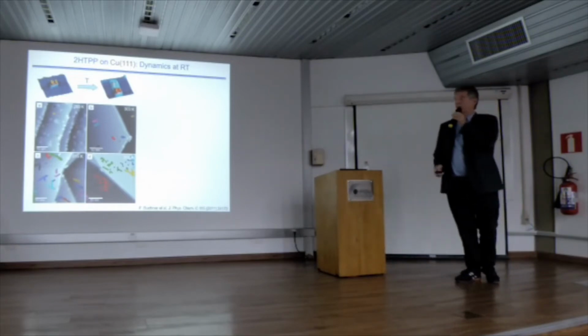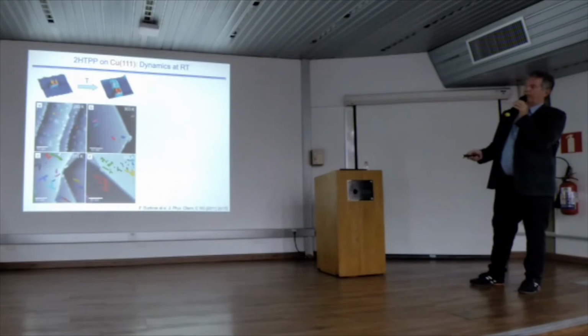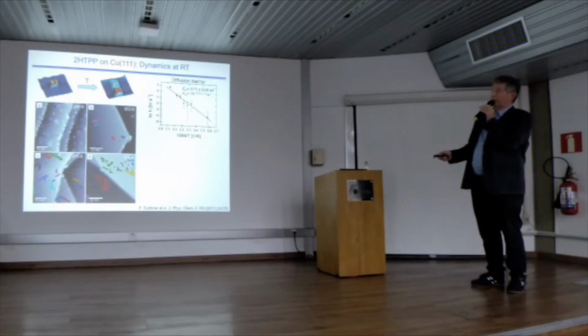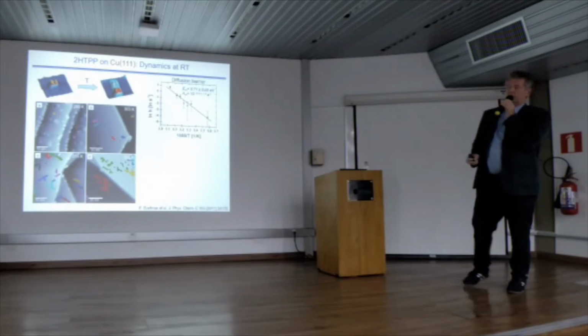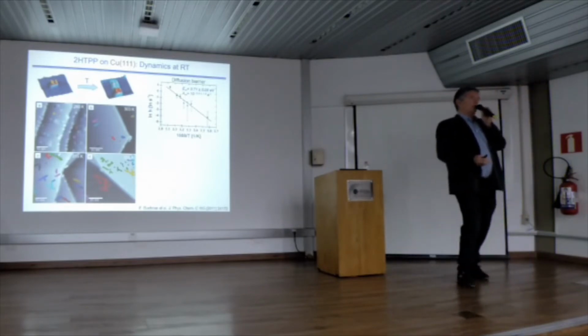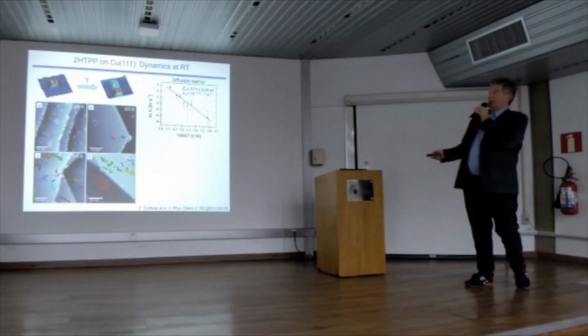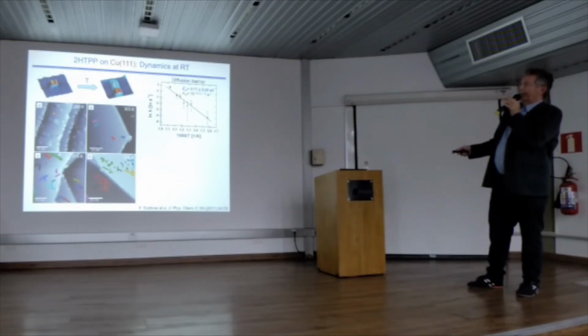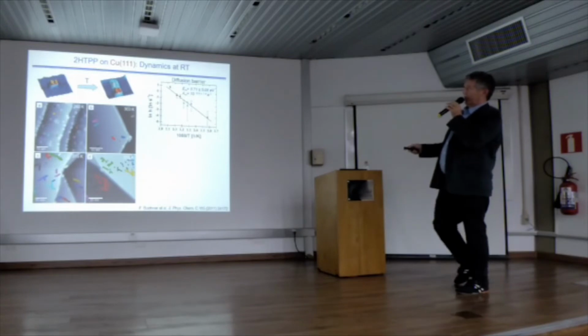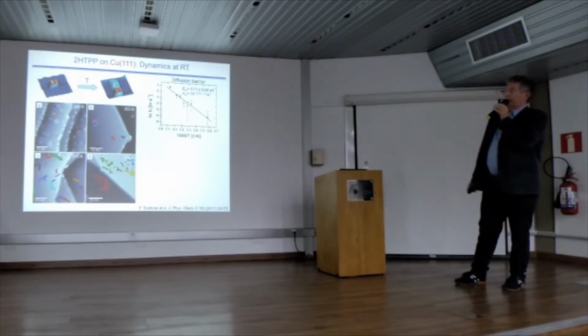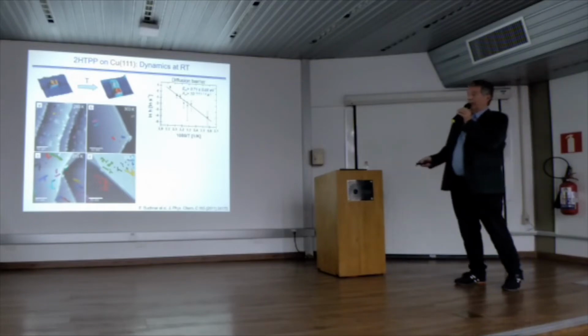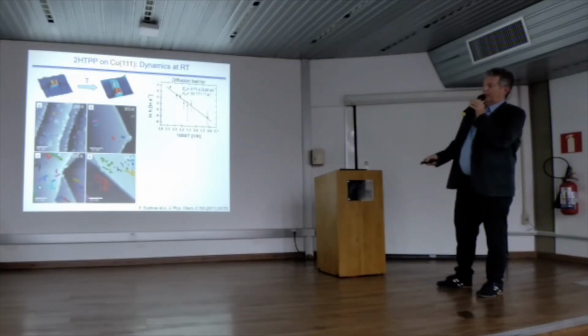and then they move in the other direction. So what you now have to do is count the hopping rate, the hops at these individual temperatures. And that's what the students did. They counted the hops, and we plot here the logarithm of the number of hops versus 1 over temperature. So this is the typical representation of an Arrhenius law. And what we see is a straight line. And if you have a straight line, you can immediately get the activation energy for this process, and this is 0.71 electron volt, and the prefactor is 10 to the 10. And then we can do the same analysis for the number of changes of the movement.